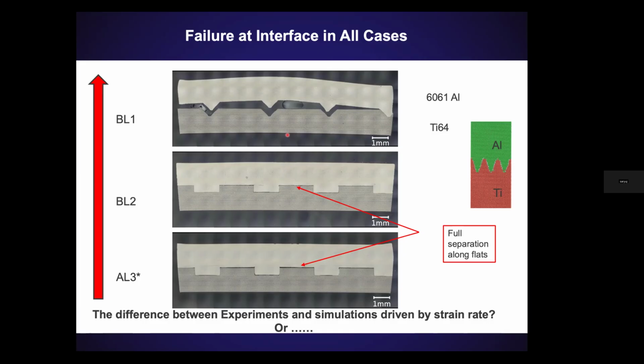There are multiple things that could be going on. One, in real materials, we have defects, right? In molecular dynamics, I just made this perfect cell with no defects. So the material is already defect starved, and the defects from the interface are the ones we did see: a higher dislocation density in aluminum, where the dislocations nucleated from these rough regions, and they probably acted as void nucleation sites. Whereas the 6061 aluminum is not pure, so it probably has a pre-existing dislocation density. So that's not a mechanism that is activating in experiments.